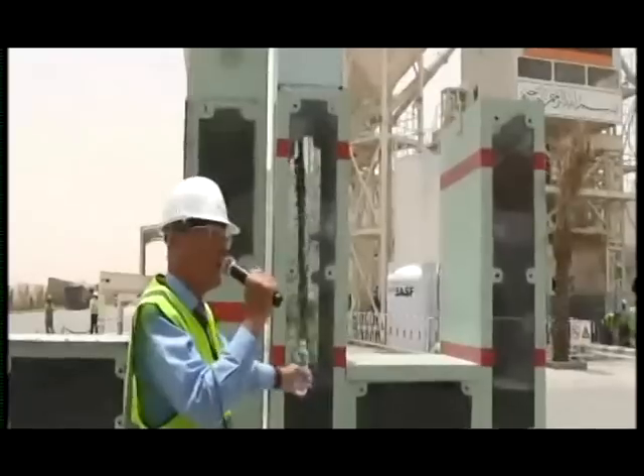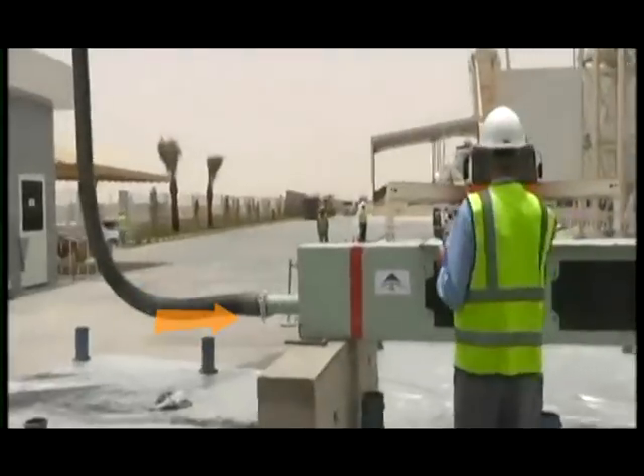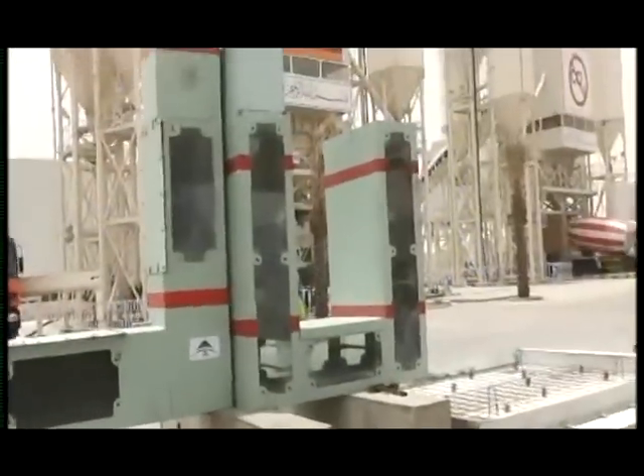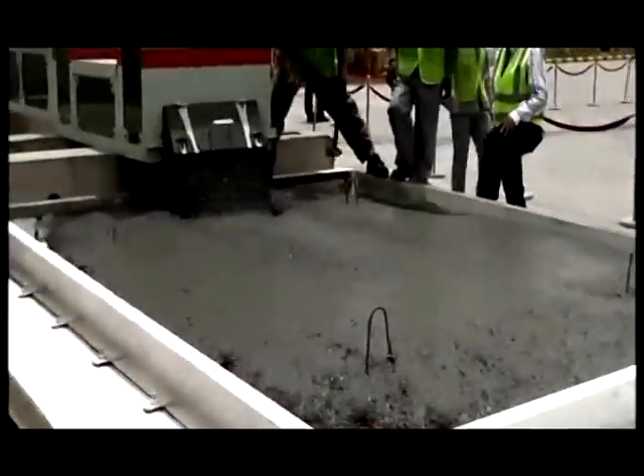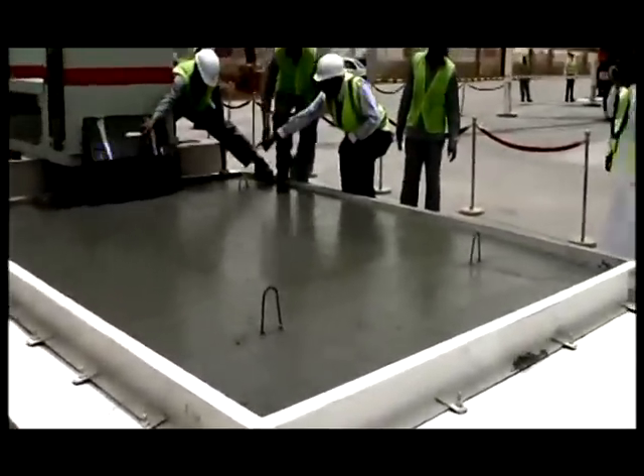In this demonstration, the concrete is being pumped only from one end along a horizontal beam, then vertically upwards before passing into a U-shaped mold. When this mold is full, a trap door is opened in the bottom of the mold and the concrete flows out and fills the slab mold. The concrete is fully consolidated throughout the pour without the need of any other form of compaction.